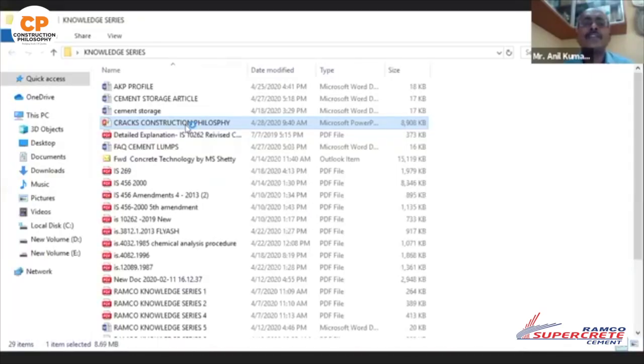So what do we do for that? What we have done at Ramco Research Development Center is that we have studied heat of hydration in detail. If you look at the cement test certificate, heat of hydration is not at all mentioned, but heat of hydration studies we have done, and we have done durability studies using RCPT and water permeability test, which takes care to a large extent of many of the deterioration mechanisms that happen in concrete. I would just like to share my screen to show you what kind of studies we have done, so that it would give you an idea of what kind of heat of hydration studies we have done at our research center.